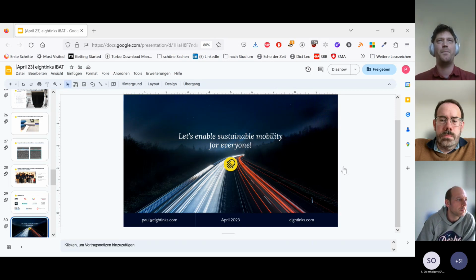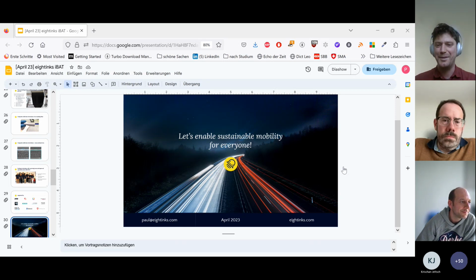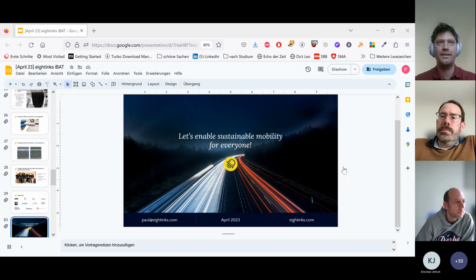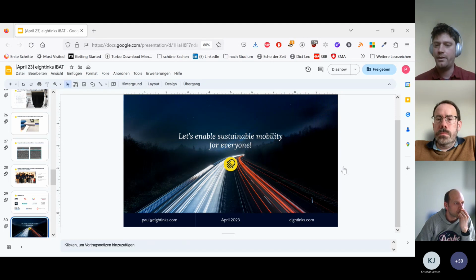Okay, it's a very good question. I think there were actually many questions layered in this one question. So maybe I'll start with saying this. I think the multilayer coating technology actually provides battery manufacturers with the most freedom of design when targeting different electrode structures. Simply by the fact that you can start layering different liquid slurries, even within a single electrode, to achieve the desired properties. So for slot die, this is really not possible because you have one layer and you only have process parameters in drying to sort of tune it. But with multilayer, you can start tuning the composition along your electrode thicknesses or along the thickness of the battery.